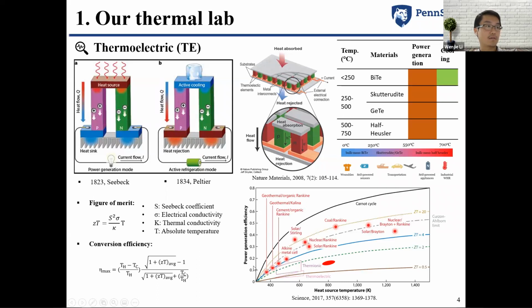And this is the power generation efficiency against the heat source temperature, compared to the Carnot efficiency. As we can see, with the increase of the average ZT of the materials, we can step by step increase the conversion efficiency and make it close to the limit of the Carnot efficiency. Nowadays, we are basically in that range with a temperature difference of about 500 to 600 degrees C, with a conversion efficiency between 10 to 15%, depending on whether it is a single layer, segmented, or cascaded device.